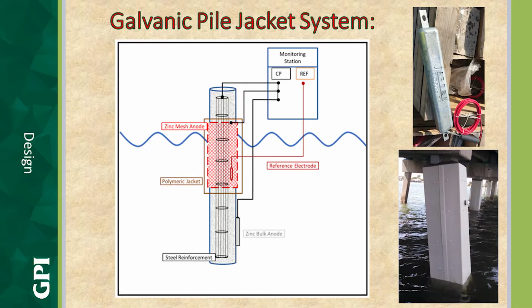So how do we apply this in a bridge structure? Let's start with a galvanic pile jacket system, which mitigates corrosion in the tidal zone. Why is that important? Because the tidal zone is the most severe area where corrosion occurs. We've got abundant oxygen and continual wet and dry periods. We wire the steel reinforcement to a zinc anode, expanded wire mesh.